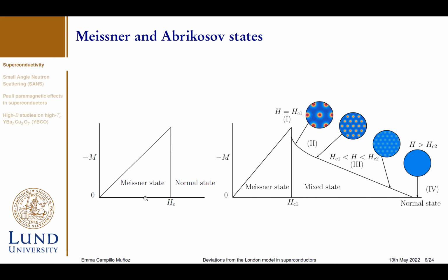However, when we move on to type 2 superconductors, they are also able to expel the magnetic field between 0 and a lower critical field, and they also show this Meissner effect. However, when we apply a magnetic field between the lower and an upper critical field, the magnetic field is able to pass through the sample in the form of a vortex line lattice, as we can see in the little picture that we have here. When we increase the magnetic field that we apply to this material, the density of flux lines will increase as well, up to an upper critical field where the material will come back to its normal state.